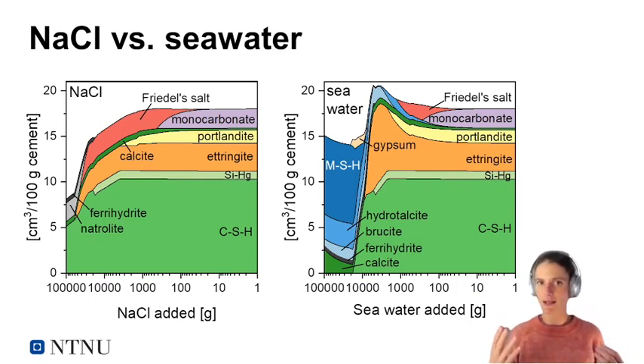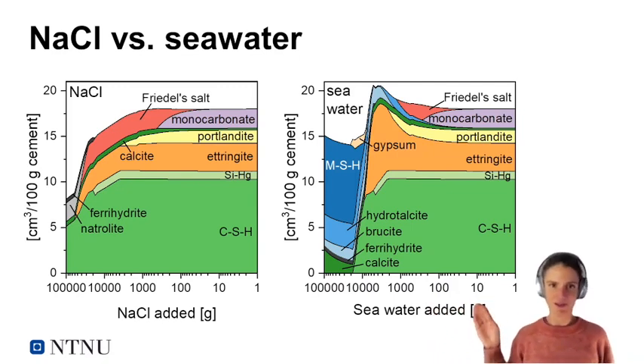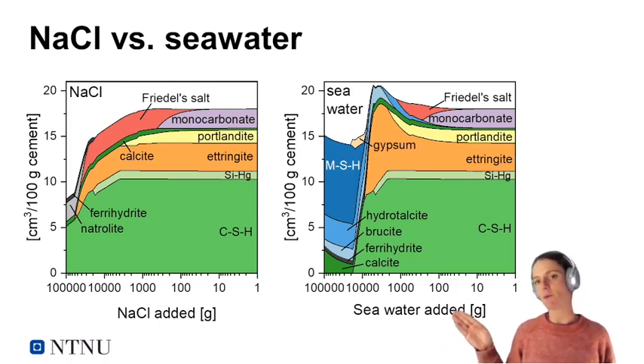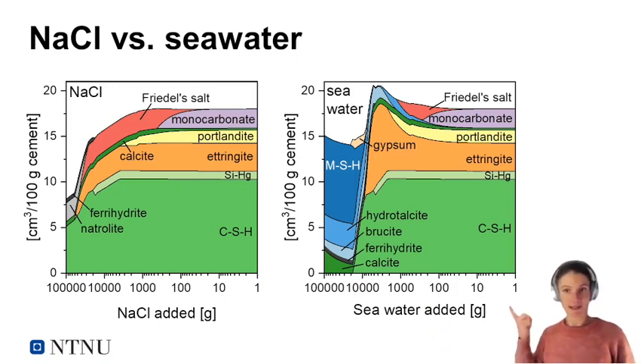We can clearly see that on the yellow phase, portlandite, it's gradually dissolving when we're adding more and more sodium chloride. So the point most toward the left, with very high sodium chloride additions, simulates what we would expect at the exposed surface. And similarly, we can do it like this here for seawater.